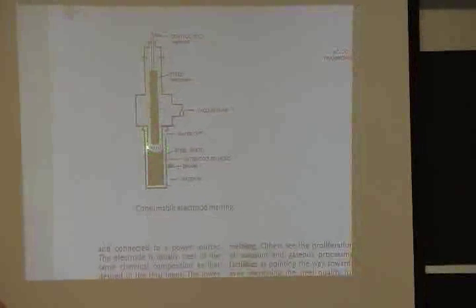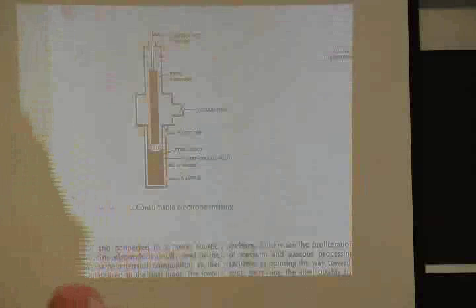Other processes, there's what they call consumable electrode melting, which is just a big single arc furnace where you actually cast a steel electrode, and then you have a water-cooled copper ingot mold, so water out, and you just run an electric arc and melt this just like a great big welding electrode, just depositing metal into a crucible. Expensive, but if you do it with a vacuum, you can get rid of a lot of inclusions and other things. So vacuum arc remelted. This material would be VIM VAR, okay?